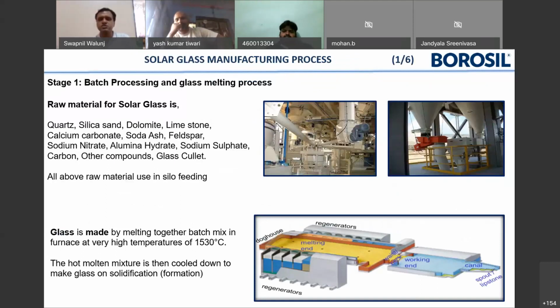The first part of the manufacturing process of solar glass is batch processing and glass melting. You must be seeing these pictures. These are loading silos. From these silos, the raw materials, let's say quartz sand, silica sand rather, dolomite, limestone, calcium carbonate, soda ash, feldspar, sodium nitrate, aluminum hydrate, and many other ingredients are loaded and fed to something called a furnace. This is a typical furnace where all this batch mix is put and heated up to 1530 degrees Celsius.